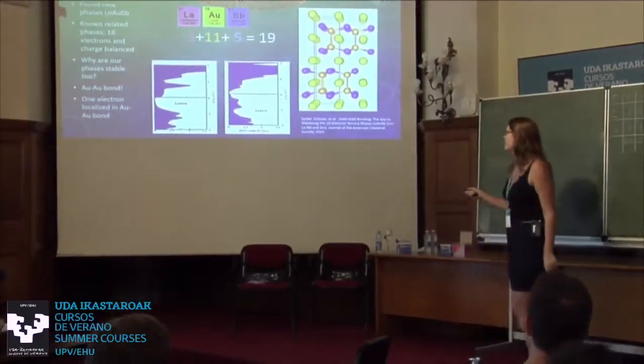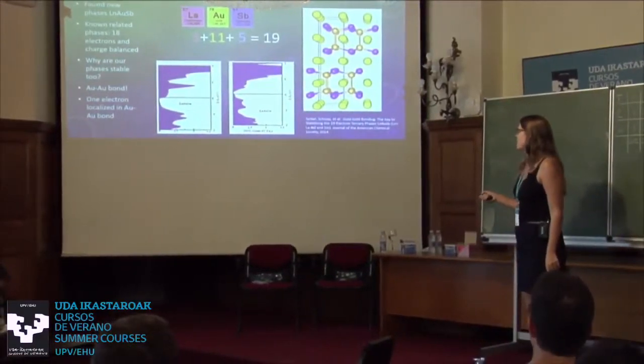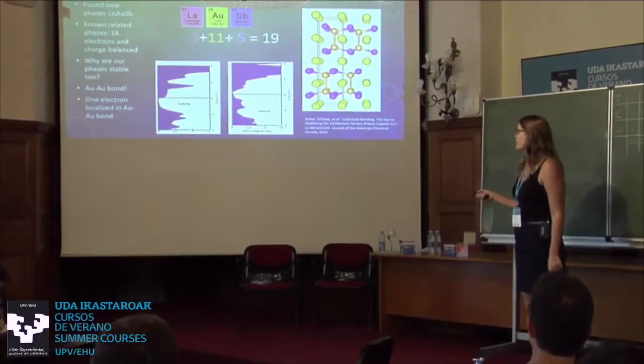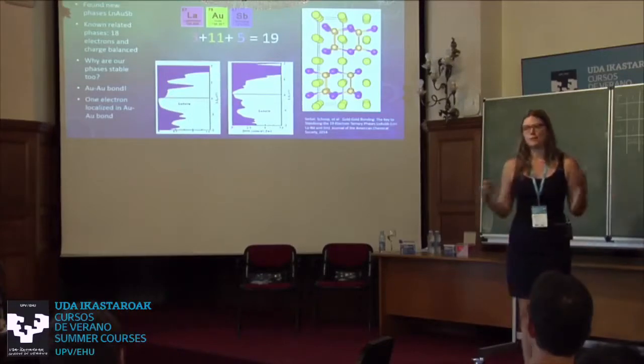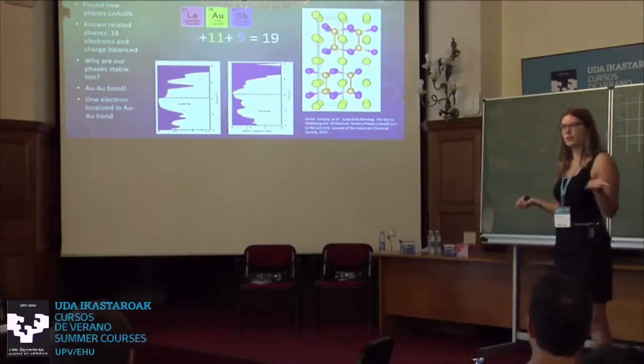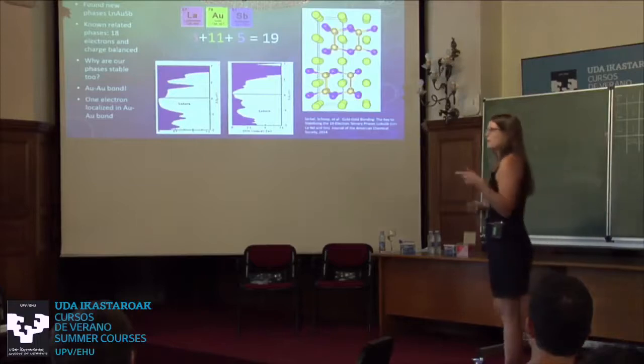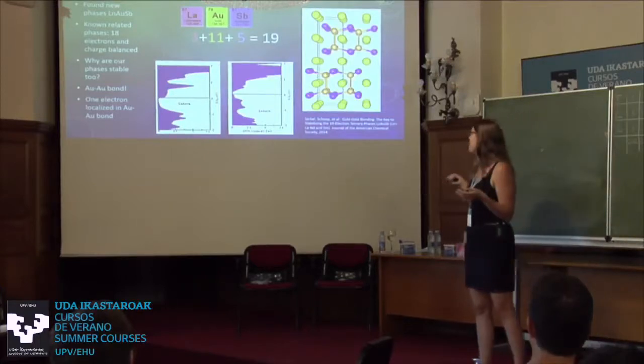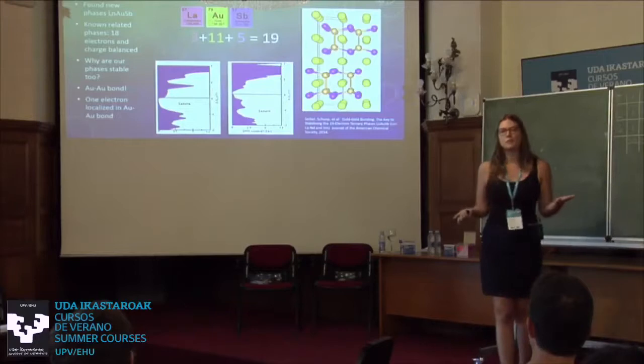And so actually, if you calculate the density of states of lanthanum gold tin, which would be the one with 18 electrons, and compare it to the one of lanthanum gold antimony, you see both of them, the Fermi level falls in a pseudo gap, so both of them are like charge balanced compounds. Okay, so this tells us that there can be bonds in crystal structures and we still have something charge balanced.